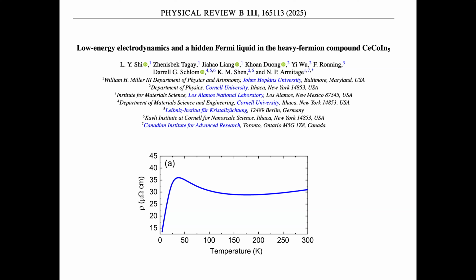This is the resistivity as a function of temperature. It shows typical Kondo lattice-like behavior. There's a decreasing temperature dependence that looks a bit like a metal, but then the resistivity starts going up, quite uncharacteristic of a normal metal. It has a peak here at about 40 Kelvin, and then starts decreasing strongly, and at even lower temperatures it goes superconducting. So this peak, where it starts increasing, is typically inferred to be the single ion lattice Kondo scale, and then there's some kind of coherence scale where this scattering that comes from conduction electrons scattering off of spins starts to be coherent, and then you enter this regime, which is here, of linear T resistivity.